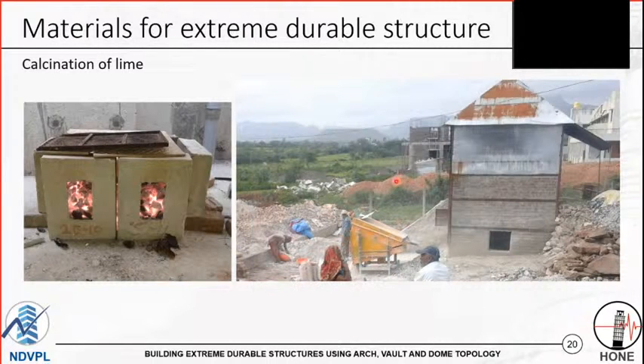And backside, here you can see the stacked hydraulic lime. I repeat, hydraulic lime and pure lime are two different things. The lime which is commercially available is a pure lime. It has no silica, so no formation of CSH bond. It's not durable. It will dissolve in water.